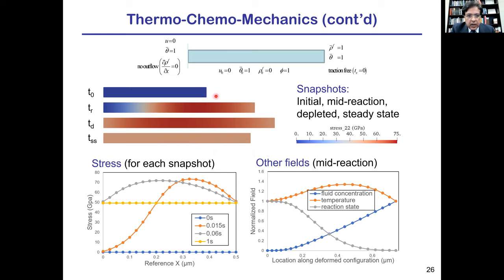We can show this: initial state, mid-reaction state, depleted state, and steady state as a function here. So this blue line shows time t0, unoriented material, unreacted material. At a later state, the mid-reaction state, where more reaction is taking place here, we see higher stress in that region and low stress in the region where reaction is not initiated yet. Once the entire domain has transformed, there are stresses built inside the material, which are thermal stresses, because thermal phenomena have not had enough time to dissipate, and eventually they get dissipated and we get the steady state.